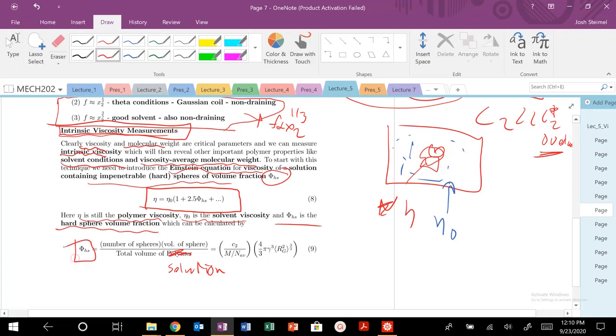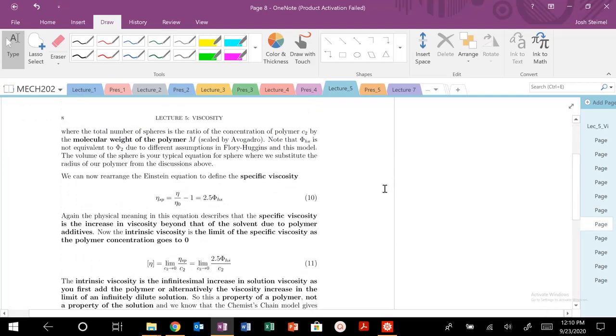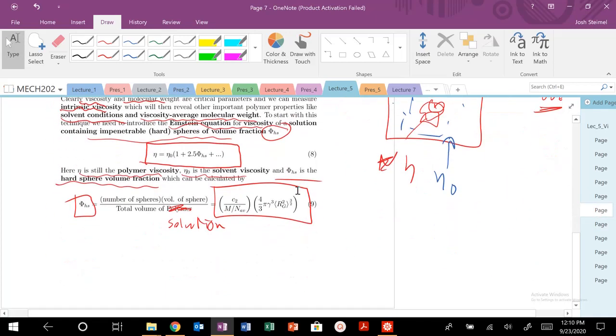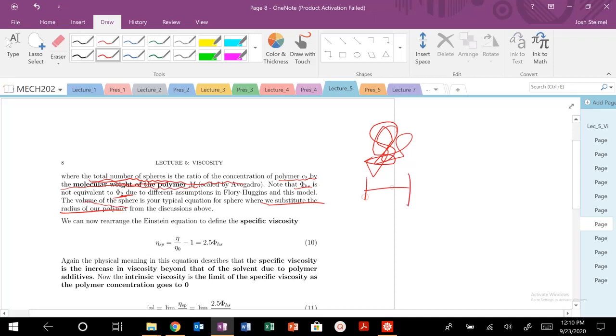The total number of spheres is the ratio of polymer concentration C2 divided by the molecular weight M, scaled by Avogadro's number. The volume of each sphere uses the typical equation substituting in our polymer radius — our hydrodynamic radius R_H or R_G. So the physical picture is that R_H represents our polymer's hydrodynamic radius in solution.